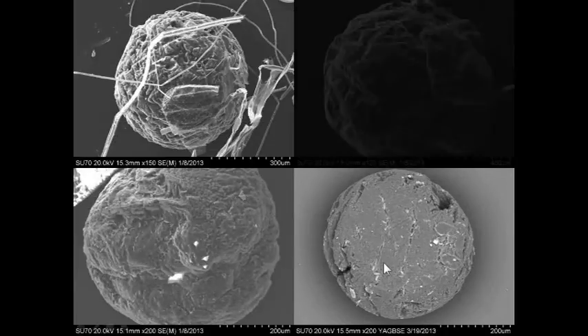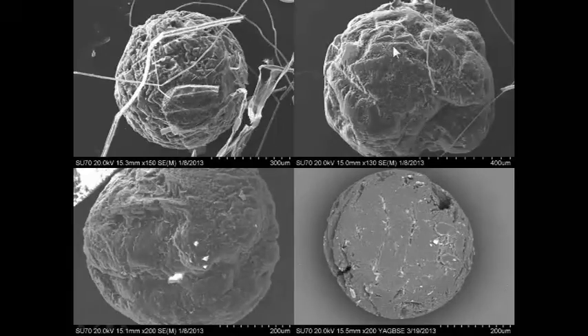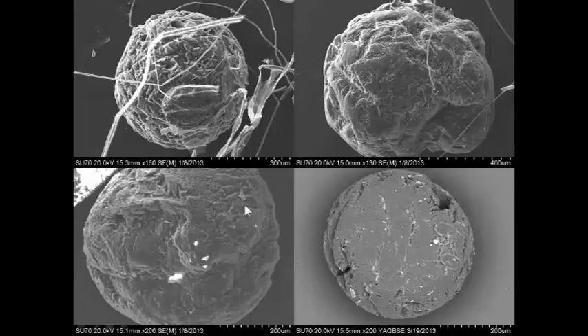Like I said, some of our particles were very inorganic in nature, but then we had these others, perfectly spherical particles, again in backscatter mode, that are very much organic in nature. Just showing you a few different images of some of the particles that we looked at, to give you an idea. You see some texture to them. If you look closely, you have diatom formation on many of these. It looks like little hairs growing on them. They're somewhat degraded because of being in the water, but they're definitely very spherical in nature as well. And this made us think, what could be a possible source for this perfectly spherical little microbead directly into the Great Lakes, and got us thinking about personal care products.